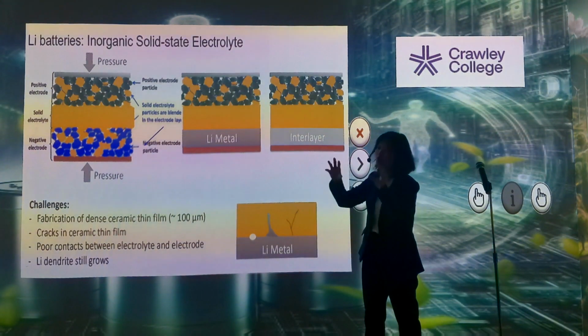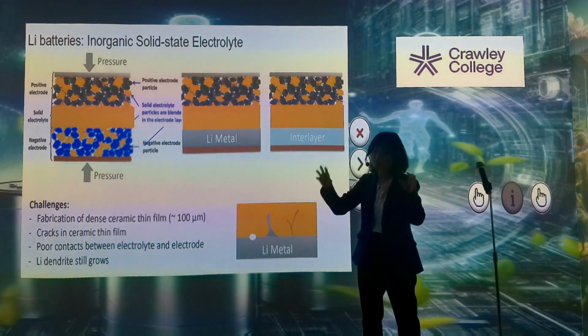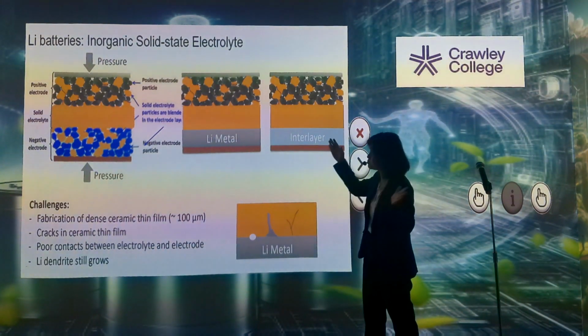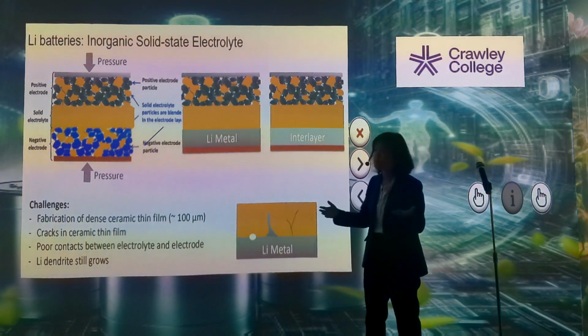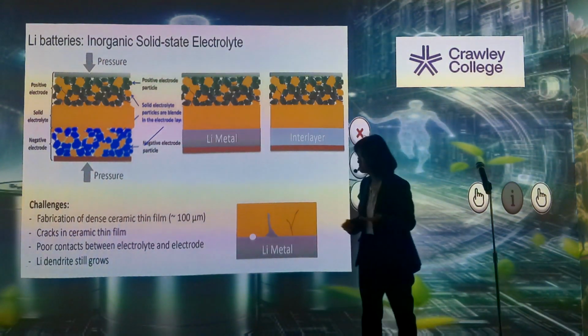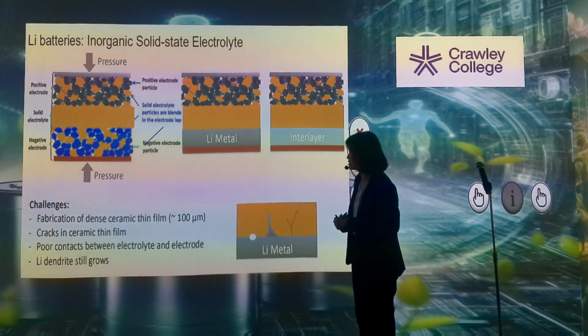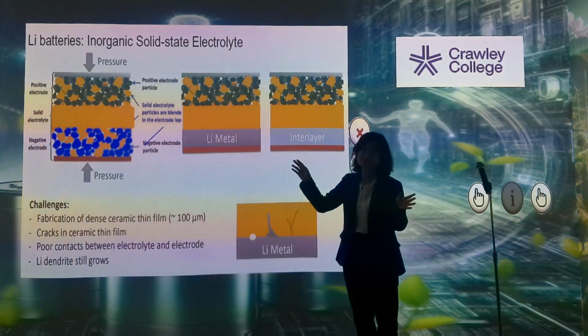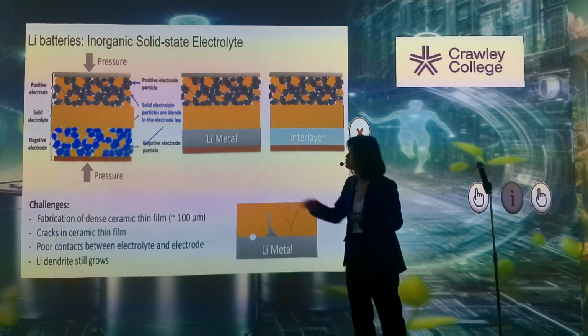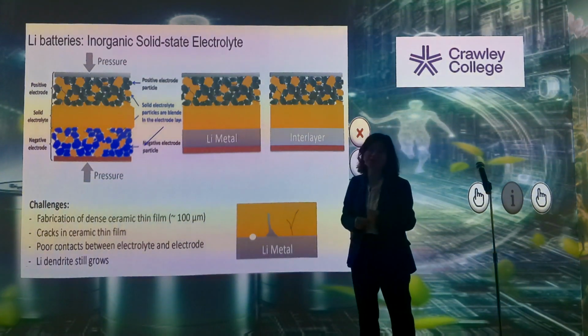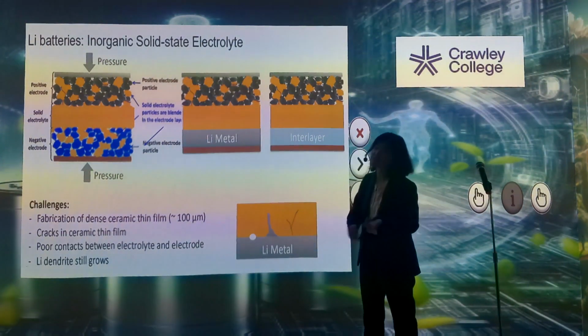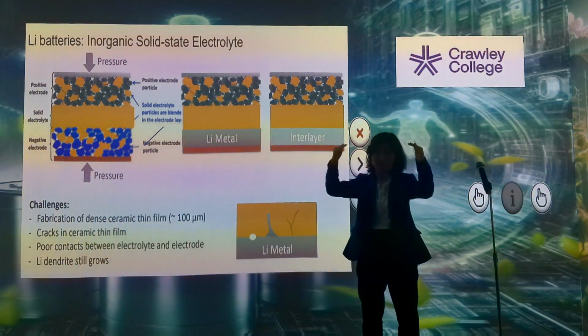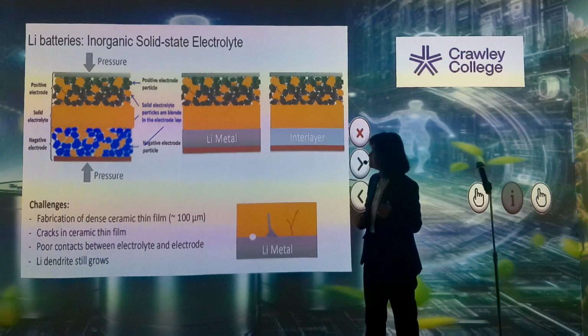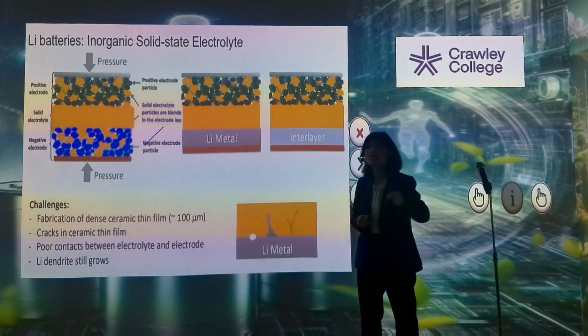All of the material inside are solid particles. So in order to create good contact, you normally have to apply pressure. And under pressure, the ceramic material could crack. Another challenge is, before they proposed the idea of this kind of inorganic solid state electrolyte battery, people thought this could prevent lithium dendrite growth because now you have a dense ceramic layer. However, recent research found that lithium dendrites still grow, although at a much slower pace.